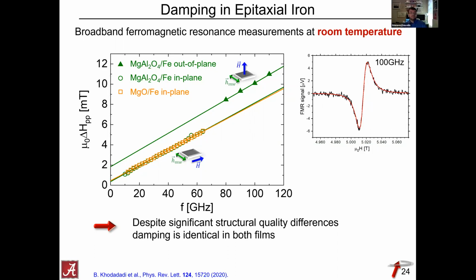There are. So one reason is you definitely want to saturate your film out of plane, and we're talking iron. So you need to be at least at a little more than 2 Tesla. So that's part of the reason. Others are that at some point you have instrumental limitations which actually limit us from going to lower frequencies. Yes, we would have loved to go to lower frequencies, but in this particular case, we couldn't do that. Okay, thanks.